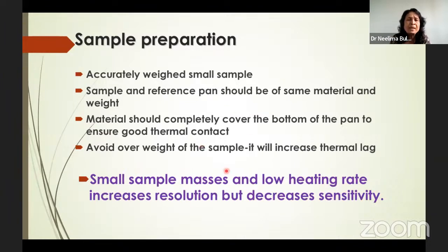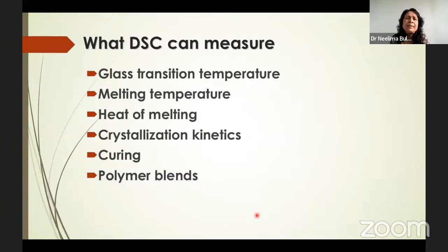So, small sample mass and low heating rate increase the resolution. But see, it decreases the sensitivity. But nowadays, with advanced techniques, I think the sensitivity has also improved like anything. So DSC can measure glass transition temperature, melting temperature, heat of melting, crystallization kinetics, curing, and polymer blends.